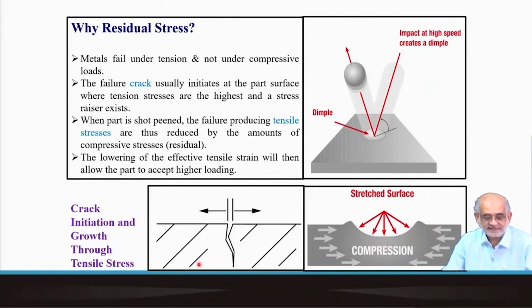Now, what is the advantage? If I have a crack like this, the crack can open and propagate further, provided the state of stress, at least at the crack tip, is acting away from each other. That means tensile in nature. On the other hand, by doing such shot peening, if I can create a uniform state of stress up to a limited depth or desired depth, where the stresses are acting towards each other, just opposite to this, then in order for the crack to propagate, we first have to convert the residual stress on the surface from compressive to tensile, acting away from each other, and then only this crack can propagate.